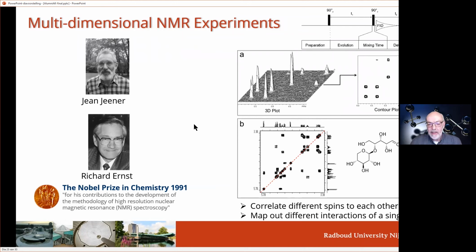So then the next step I'd like to point out, and we also use that for this study, is that NMR is not confined to just one experiment. Get a spectrum, do this radio frequency pulse, measure your signal, and generate your spectrum out of that. Actually, in the 70s, Jean Jeener proposed that you could do multiple radio frequency pulses and define different time dependencies between these pulses and vary them in a systematic way. And in that way, you can, for instance, create two-dimensional spectra, where you would have peaks mapped out in 2 dimensions.